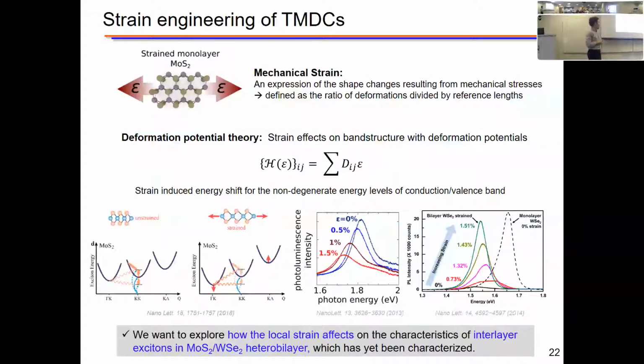For example, if we apply tension, the energy at the K-gamma valley is energetically lower than K-K, so there's an optical transition from direct to indirect. That can be seen by photoluminescence measurement. So what we're interested in is what will happen if we layer these two materials.